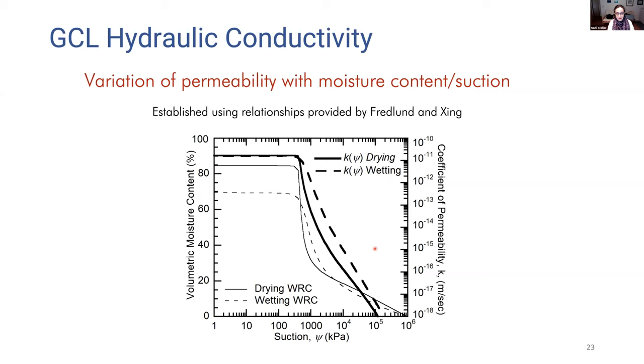We also looked at hydraulic conductivity variations, and we did this with theoretical analysis using the moisture suction relationships and converting those to permeability relationships using the formulations provided by Fredlund and Xing. This is a double Y plot where we have volumetric moisture content on one side and the coefficient of permeability on the right side on the y-axis, and we have suction on the x-axis. We have two sets of data shown.